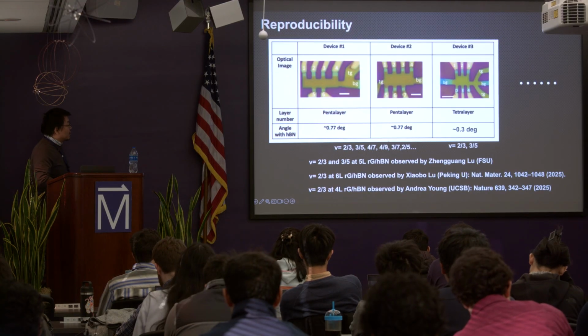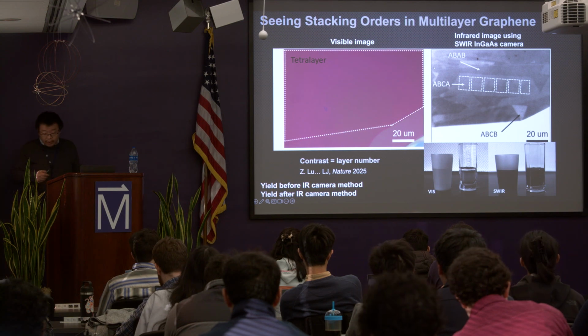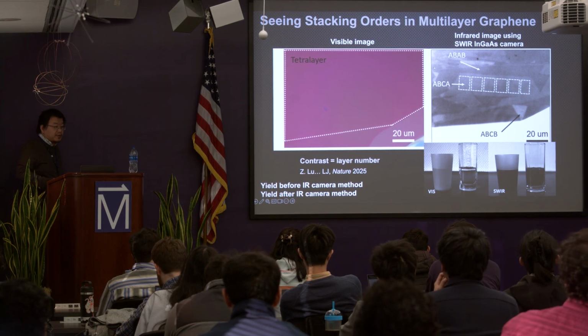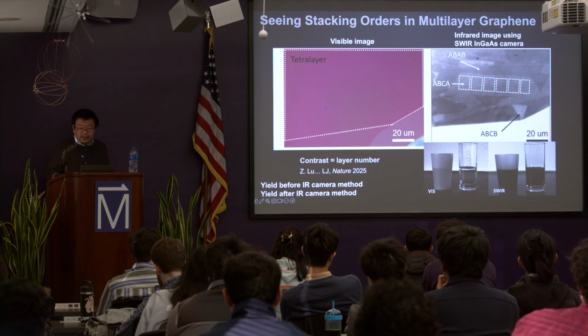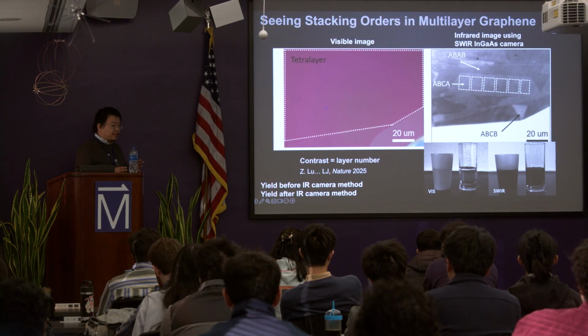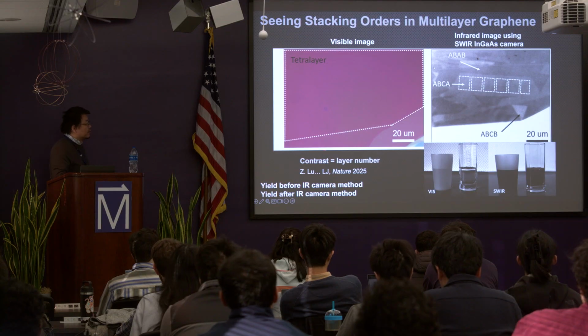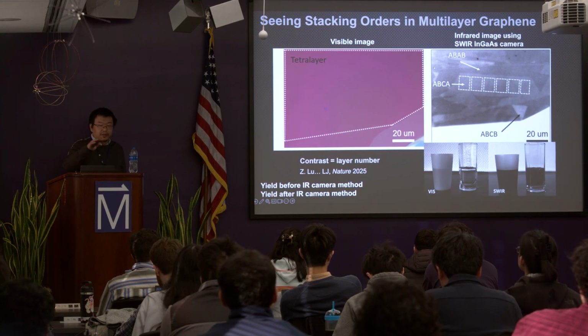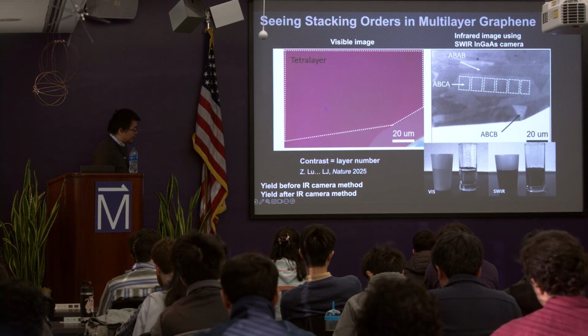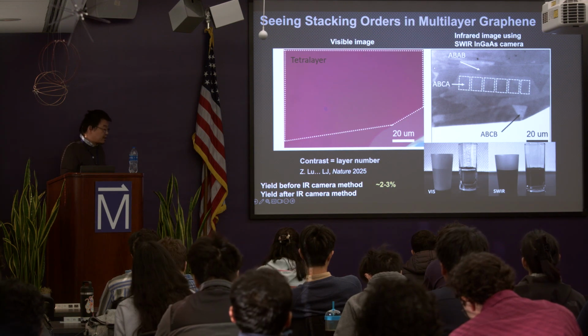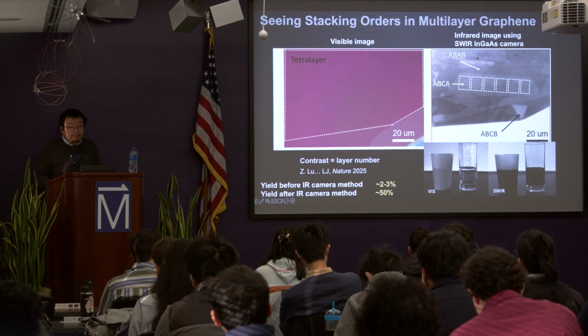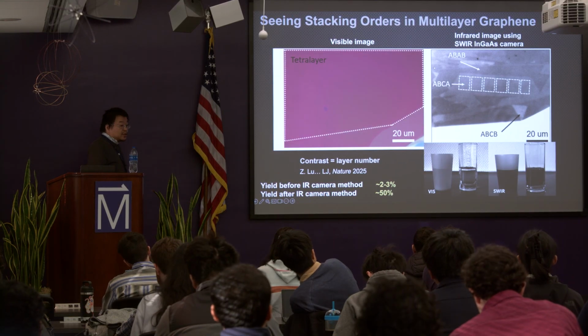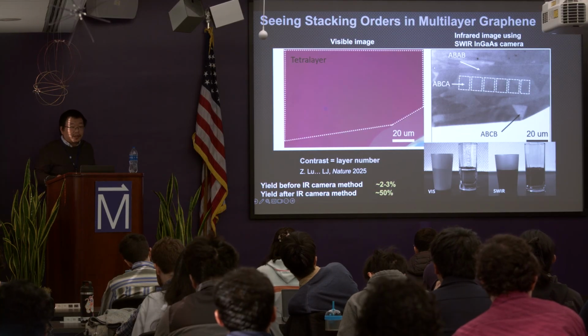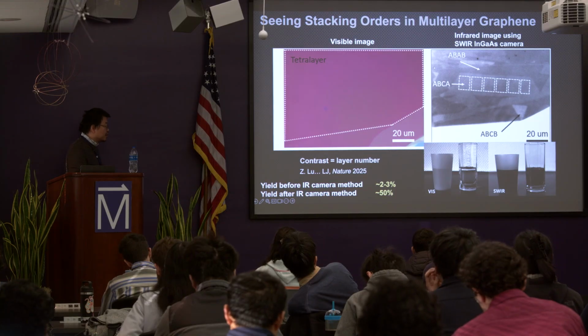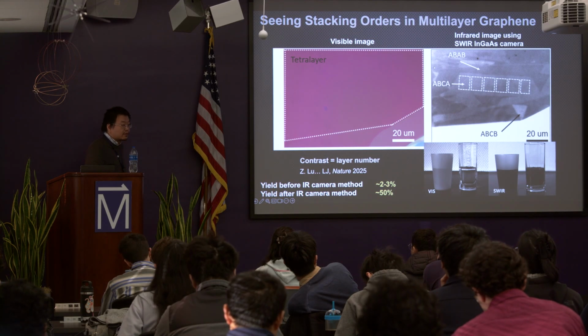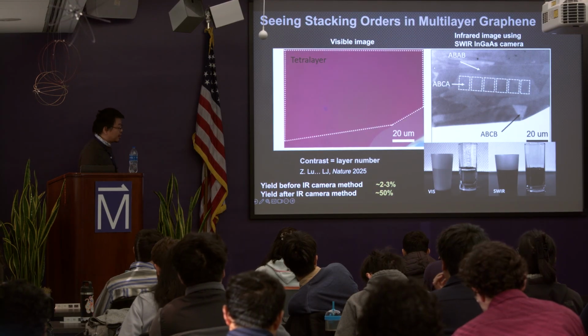So this is how reproducible all the devices are. It's all because of the improvement of our sample fabrication process. Before, you only had 1-2 devices that you could play around with, because that takes years to make. Now, by using a certain optical method, you can better see the difference between the different stacking orders, and this hugely improves the fabrication process. Before, you only got something like 2 to 3% yield, and now you almost get half, like 50%. In terms of time, the first few devices took a student a year or more for the fabrication. Now each student has a few tens of devices in their hands. So that's how you check the reproducibility and gain confidence about all this.